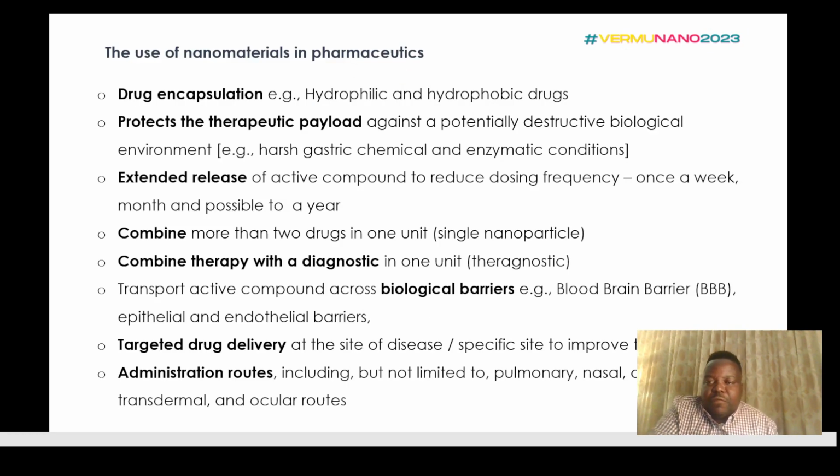These are some of the benefits of using nanomaterials in pharmaceutics. The important thing is that nanomaterials allow us to incorporate both hydrophilic and hydrophobic drugs within their structure. Nanomaterials also protect the therapeutic payload against destructive biological environments, such as the harsh gastric chemicals within our stomach and enzyme conditions within our bloodstream. Another advantage is that they can extend the release of the active compound to reduce dosage frequency, to once a week or monthly, and possibly even a year.